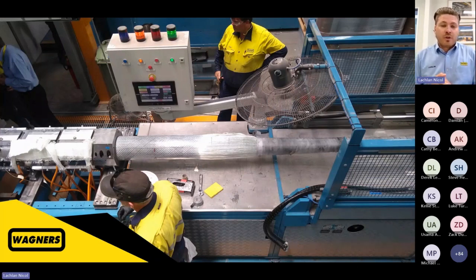This is a bit of a bird's eye shot just to show you the transition. So this is a new startup process. When we change a die, we need to pull through all of the glass. So you can see that little transition from glass package dry, and then once we started injecting the resin, that then starts curing it, and that creates this nice hard shape, which then goes through the pullers, and that's just a continuous process, 24 hours a day, 7 days a week, pultruding hard pultrusion. Sorry.